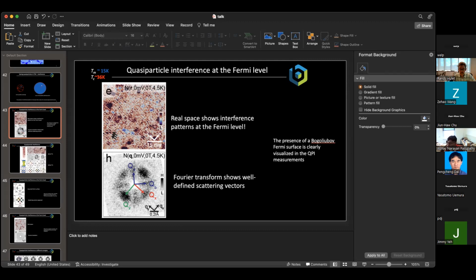Could you clarify what you mean by studying phase boundaries? Yes, so in our work, because we have an inhomogeneous density, we can see spatially resolved transitions from the FFLO state to a ferromagnetic state, or FFLO to a BCS-like uniformly paired state. Yeah, I see. So I was wondering if you had phase boundaries in your data, and if so, what are the phases that you see? Yeah, so far this is an observation in a single sample, and the only thing we've explored is temperature, and there the phase boundary is the magnetic transition that we see.